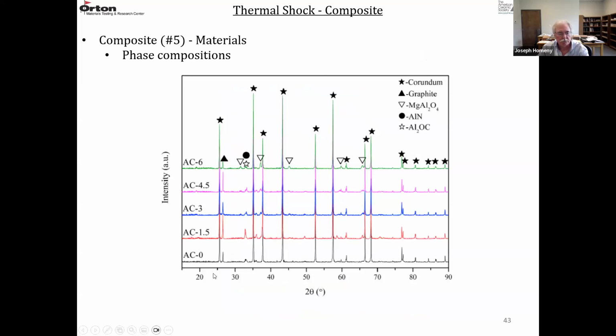The X-ray diffraction shows AC 0, AC 1.5, AC 3, AC 4.5, and AC 6. So they're going up in the carbon spinel powder additions. The stars are corundum or alumina. That content is high in all of these. The triangle is graphite. It's present again in all of these, but it's a lower percentage. And then the minor phases, these two, are aluminum nitride and aluminum oxycarbide. The solid circle and the open stars are forming in trace amounts.